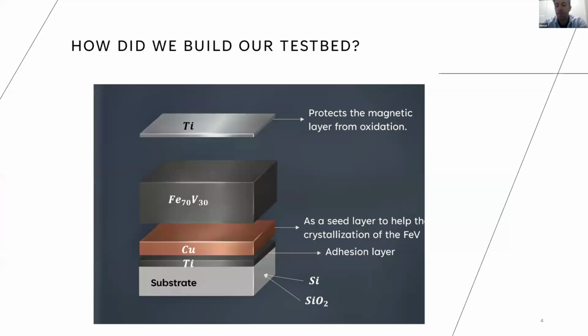Okay, so let's start. I'm going to talk a little bit about my sample. To be able to see this subtle whispering, we need our iron vanadium layer to be perfect, with a low defect crystal structure. For that, we need a crystal template for its growth, and our choice is copper. A thin layer of copper forms naturally in an ordered surface, and its atomic spacing is well matched with iron vanadium.